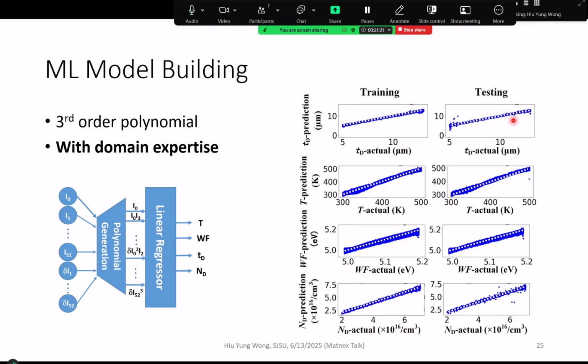And we apply this to the testing data. Again, they match the simulation, the actual value, very well. Again, what we are doing is that we put in the simulation IV curve, correlate it to the structure or defect parameter. We train the machine, then put in a new IV curve and ask it to predict what are the temperature, work function, etc. And they are perfect for this 150,000 data. Okay, so this looks like a good machine, right?